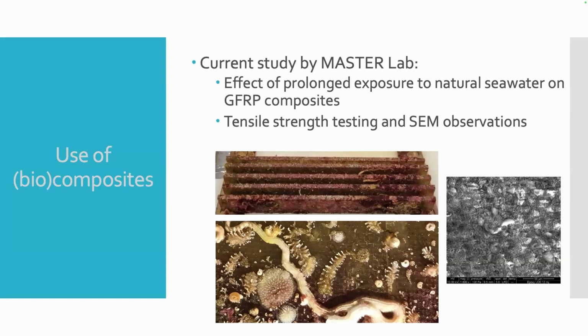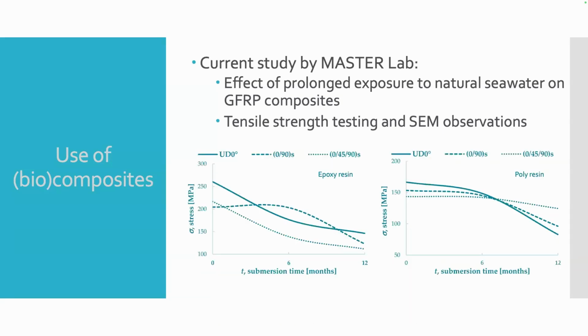And we noticed that there is a larger mass of these small marine microorganisms on the polyester resin. That is what we saw just by weighing the mass of the coupons and by looking with the optical microscope. What we see when we dug a little deeper is that these microorganisms have found their way into the structure of the material, making voids in the structure, and those voids can act as crack initiation points. We tested these coupons to see how well they retain their tensile strength, and you can generally see that the tensile strength of this type of material is lowered when you expose it over a period of time to the natural sea environment.